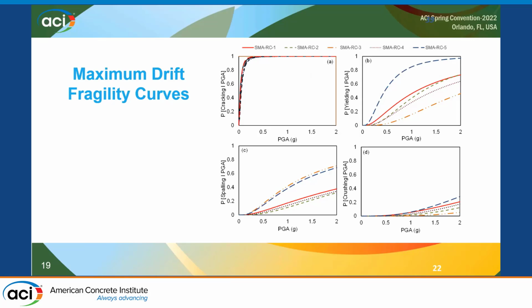Here in this figure, we can see the results of the maximum drift fragility curves. The first figure is for cracking, or damage state 1. We can see that all the 5 SMA bars had similar performance in terms of cracking. But when we go to yielding, we can see that SMA-3 had a very low probability of yielding, but SMA-5, the blue one, had the highest.